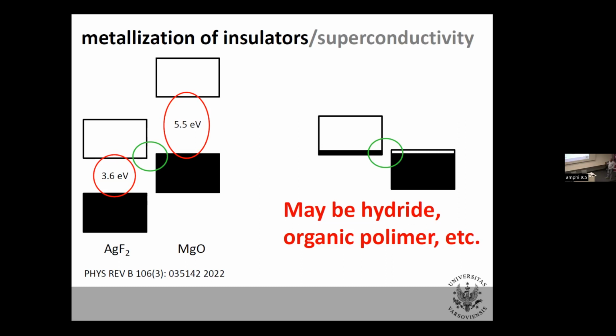Okay, so as I said, this could be good for metallization. The trick is, the valence band of one substance and the conduction band of another substance should overlap, and they will mutually dope each other. Do you know what effort there is to metallize AgF2 with a gap of 3.6 electron volts? You can use 1 terapascal. It will not metallize. The same with magnesium oxide, even broader band gap. Ultra high pressure people do such experiments, typically in the range of few hundreds gigapascals, sometimes a terapascal. You cannot metallize magnesium oxide. The band gap is too large. But use the trick of overlapping its valence band with the conduction band of an oxidizer at a distance. You will get metallization.